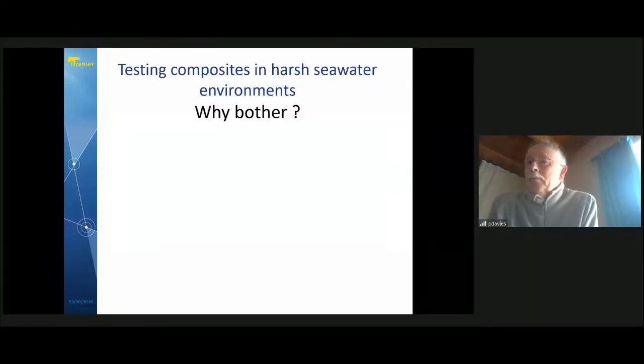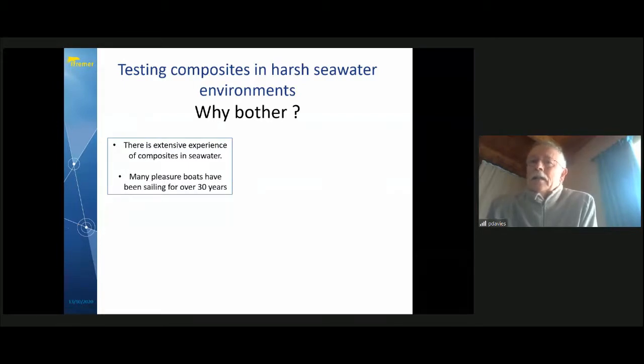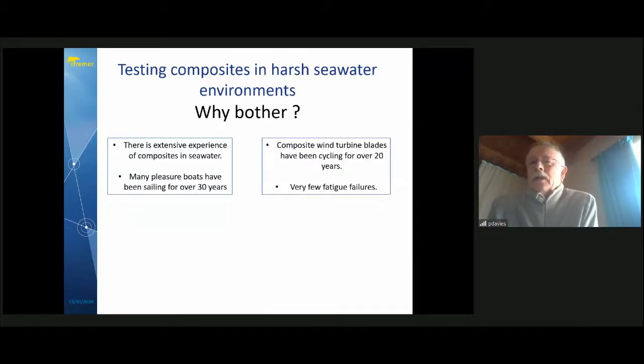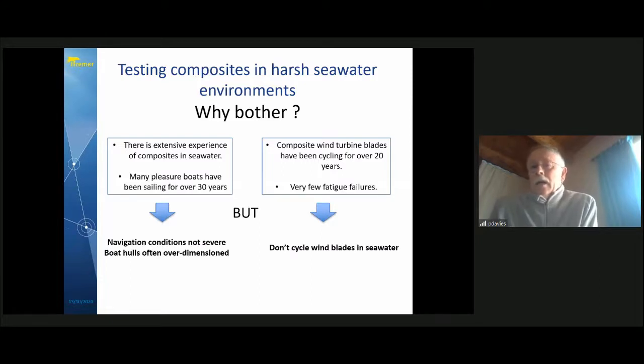The question is testing composites in harsh seawater environments. And I guess the first question is, why bother? It's expensive, takes a lot of time. We know that there's a lot of experience of composites in seawater already. Pleasure boats have been sailing for over 30 years at least. Composite wind turbine blades have been cycling for over 20 years, very few fatigue failures. But what we also know is that most small boats are not very highly loaded and not very often used, and they tend to be over-dimensioned, and that we don't cycle wind blades in seawater, or not very often. So it's probably a good idea to check, and this was what we decided to do, I guess, about 10 years ago. Next slide, please.